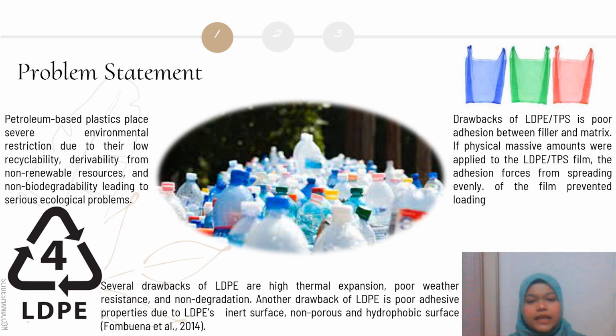However, the properties of films and the performance also depend on other factors such as interfacial compatibility between the components, miscibility, and properties of individual components. One of the limitations of LDPE TPS is poor adhesion between the filler and matrix. If physical stress was applied to the LDPE TPS films, the poor adhesion of the film prevented loading forces from spreading evenly. By adding a commercially available compatibilizer, PEGMA, the miscibility between granular starch and LDPE will improve and will encourage interfacial adhesion in LDPE TPS. Therefore, this study presents new knowledge and future development of the tensile and thermal properties of LDPE TPS films and the effect of PEGMA as compatibilizer.